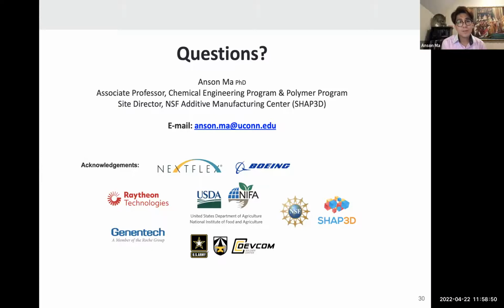Yeah, so yes, that's also a great question. The one that I showed here is the fast disintegrating. But what we have recently done with the sponsorship from the company is that we can now make sustained release. What you do is, in the formulation, you have something in the powder that could swell, so space filling. It poses some print challenges because sometimes samples just swell too much, so you really have to adjust the process parameters. But you can mix things. Imagine that it's a composite, and if you have a component in the powder that will swell when it's exposed to the binder, then you can fill that space. So when the drug is released, it's actually through the gel matrix. But you have to go back, and in our case, we had to reformulate, because otherwise the one that we showed just falls apart very quickly. Yeah. All right. Thank you.